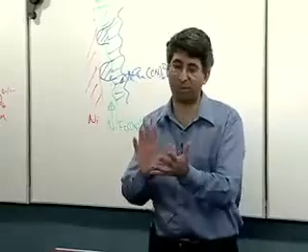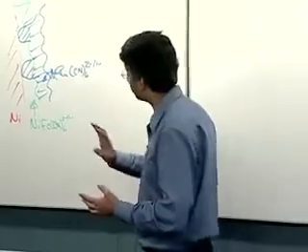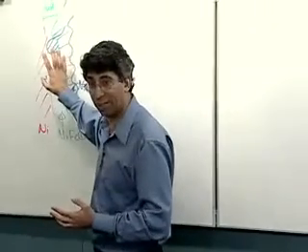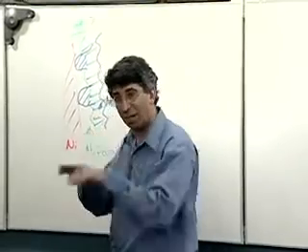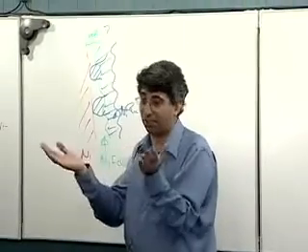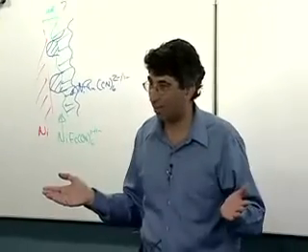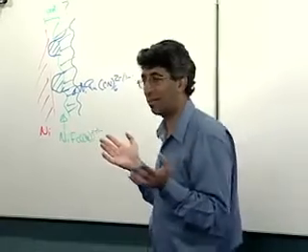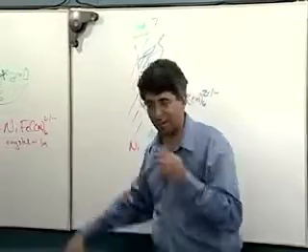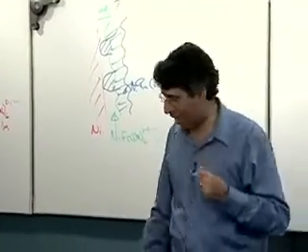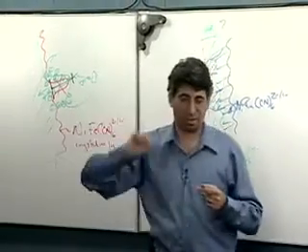And then we did another experiment where we took a ring disc electrode and we derivatized the disc with this material, nickel disc, and then we have the ring set at a potential where it will detect the ruthenium cyanide if it comes off the disc, and we're rotating it and simply ask, can we detect any ruthenium cyanide this way? And the answer is no again. So we're now convinced that if there is some ruthenium coming off, it's not enough to do this catalysis at the rate that we are observing it. So we still have the problem of how do I get an electron from here to here?